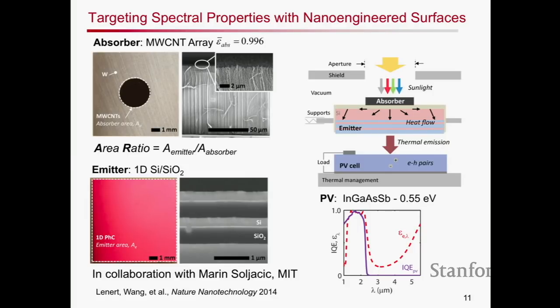What we decided to do in this case is now pattern this absorber structure so that it tries to capture all of the light in the form of heat, using a multi-walled carbon nanotube array, which is well known to have a very high emissivity or absorptivity close to 1. And what we've done here is that we played a trick with the geometry in a way.